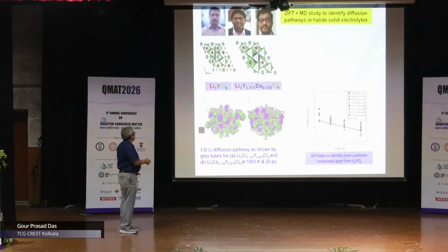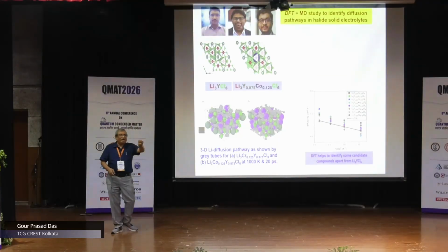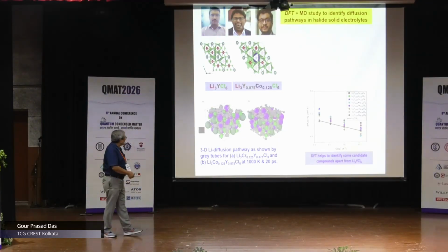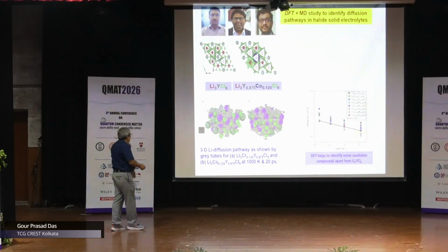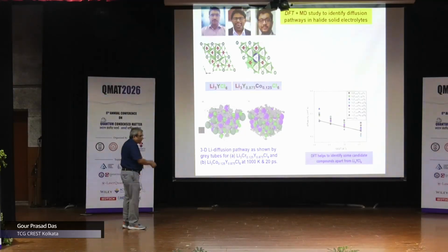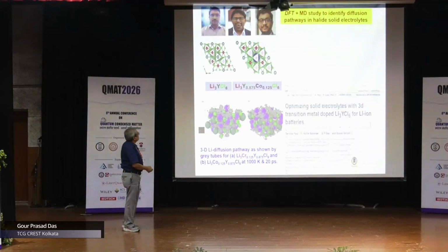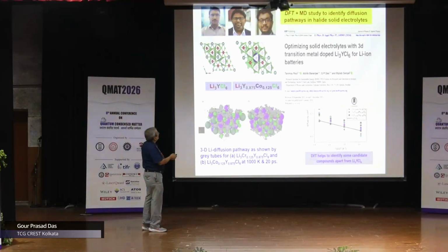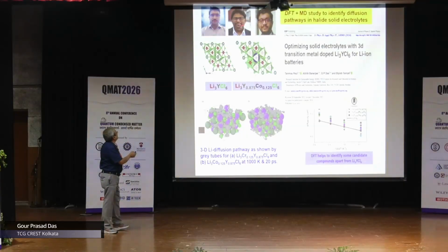And we have also done the classical molecular dynamics. Whatever you are seeing, the puddles, these are nothing but the lithium going from the cathode to the anode. And the molecular dynamics is showing you the 3D lithium diffusion pathways as shown by the gray tube. These gray things, these puddles, whatever you are seeing. And these are the lithium and yttrium and the transition metal atoms. So this is a snapshot which shows how the lithium is actually going from cathode to the anode. And the details are given in this paper which we published, optimizing solid electrolytes with 3D transition metal doped Li3YCl6 for lithium ion batteries. So these are my colleagues, and Ovik is an experimentalist.